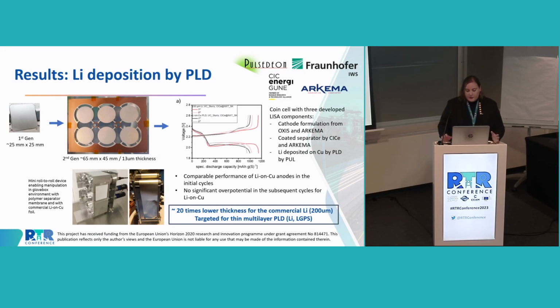This pulsed laser deposition is not only meant for lithium, but also for the deposition of LGPS, so we can build this layer-by-layer lithium sulfur battery. One question that I almost always get is, okay, you say that LGPS can be done by pulsed laser deposition, but there are a lot of other methodologies where you can do it, for example, sputtering or so on. And that is true. There are other methodologies that can be used to create this layer of LGPS. But there are 2 points that no one is taking into account. The first one is that you can do very, very thin layers with pulsed laser deposition, and you can do this multi-layer of not only LGPS, but also lithium, to obtain this multi-layer battery. So we reached this target to prove that it can be used to do this multi-layer system.